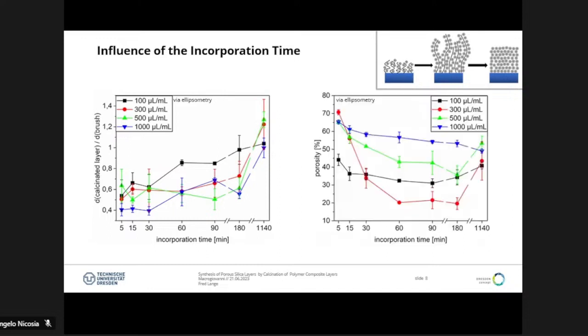But as you can see here, the porosity strongly depends on the concentration. And this slide shows that just by changing the concentration of the nanoparticle solution, very different porosities can be achieved, which means that the process can be tailored to the demands of the customer.